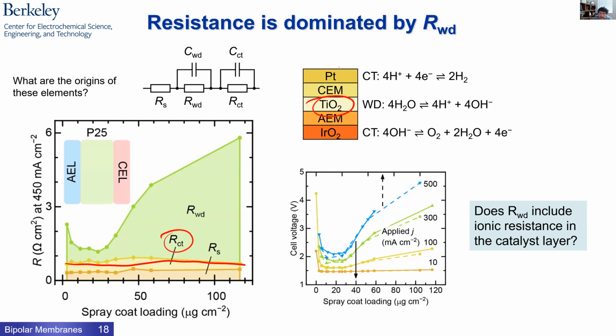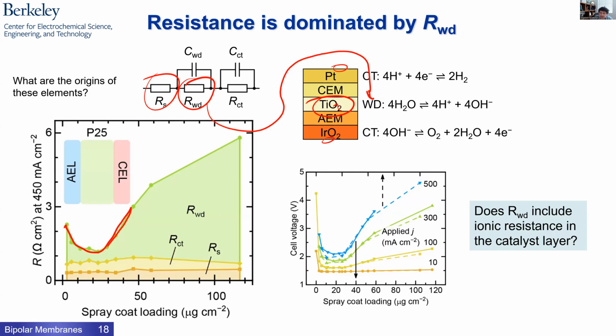Of course, that makes sense because these reactions here and here are happening spatially separated from where water dissociation happens. So that's expected. But this RS value, this is the ohmic part of moving things around. That one is increasing a little bit, but not very much. The vast majority of why you get this U shape is from this water dissociation resistance, which we had attributed to the kinetics of this reaction, of generating these species and driving that water dissociation process. So that's not what we expected. So why might this be?